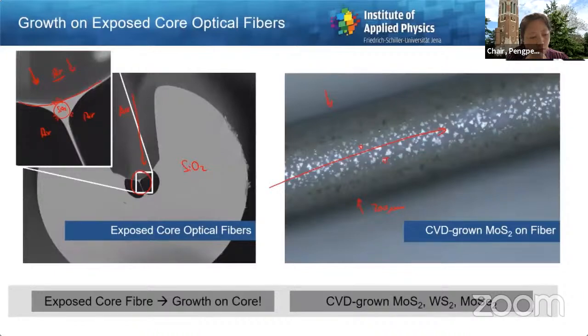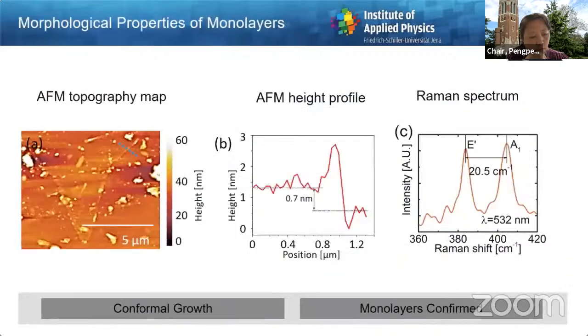This entire thing has a diameter of roughly 200 micrometers, and you see these nice monolayer crystals being grown on the optical fiber. Now, at first you need to convince yourself that these crystals that you observe really are monolayer crystals. So we measured quite a lot of AFM and Raman maps. And what you basically see is under the AFM, you get a height of these crystals of about 0.7 nanometers, which is just what you expect for a monolayer. And you get a Raman shift of 20.5 per centimeter, which is also what you would expect from a monolayer. So we've confirmed that we really have a conformal growth of monolayers on these fibers.